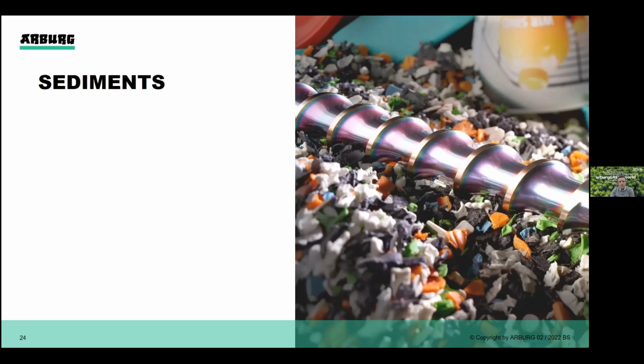Another aspect concerning the processing of regrind that has not been dedusted: the dust content, especially when we process the grists, can lead to deposits on the screw. In addition, the regrind can also contain impurities that are harmful to the screw and to the barrel as well. Our answer to these deposits is the correct use of coating technology, and we therefore recommend a chromium nitride coating, CrN coating, as you can see on the picture, to reduce deposit formation and also provide increased wear protection at the same time. So this was a really brief overview of our hardware features.